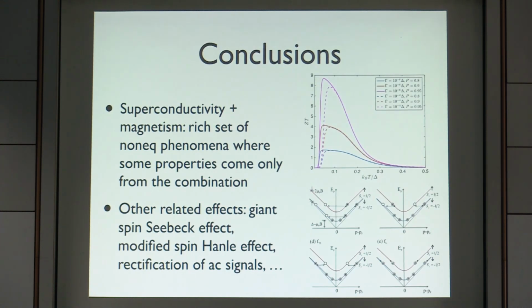Okay, so this is a concluding slide. I have shown you that if you combine superconductivity and magnetism, you get effects that neither of these systems exhibit alone, like this huge thermoelectric effect. There's a rich set of non-equilibrium phenomena, and I did not study even close to all of them that have been studied. Yesterday, we heard about this absolute spin valve effect. There are other related effects like this giant spin-Seebeck effect. Even without a spin polarized interface, this spin split superconductor holds this spin-Seebeck effect, meaning that a temperature gradient drives a spin current.